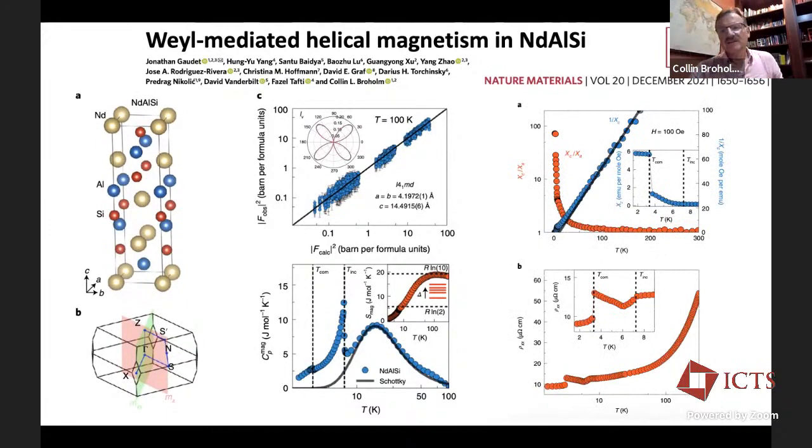Let me show you a little more bulk data, or thermodynamic data, here. The susceptibility is quite highly anisotropic. It's an easy axis system. The moments are predominantly along the c-axis. You can see that as we go through the maximum in the specific heat, depopulating the 4 excited doublets, that's when we end up having a very enhanced Ising-like susceptibility with a big susceptibility along the c-axis.